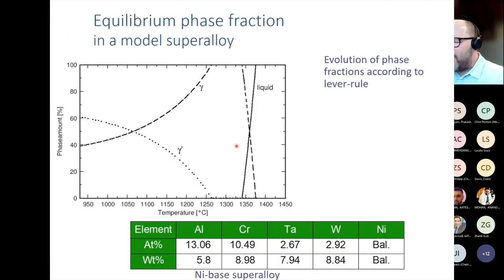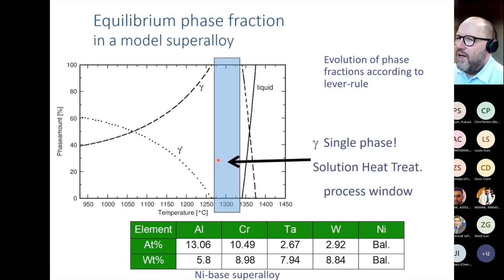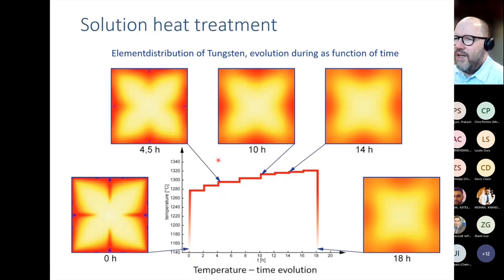So these alloys are typically solution heat treated. There's a region below the solidus temperature and before the gamma prime solvus temperature, where the alloy is exclusively single phase gamma. And typically we heat up the alloy into that temperature range in order to homogenize the alloy. So we've done simulations for that going through a multi-step heat treatment.